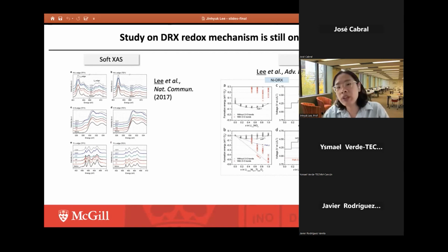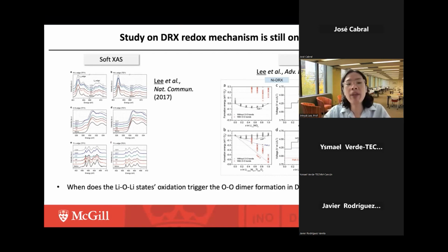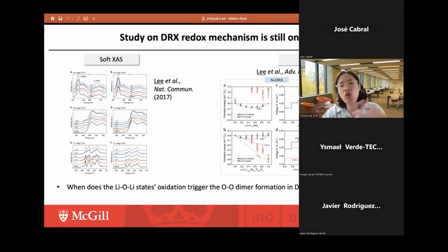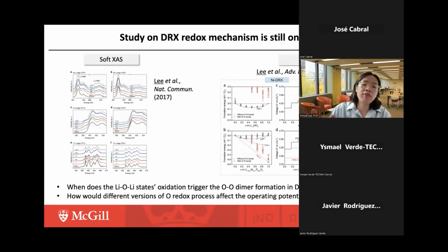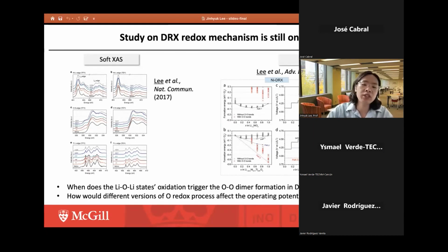Basically, I've been doing this further study to understand when this lithium-oxygen-lithium state oxidation triggers different types of oxygen oxidation mechanisms, including oxygen-oxygen dimer formation, forming superoxide or peroxide in the DRX structure. Because forming different versions of the oxidized oxygen species can affect the operating potential of the DRX and the cycling kinetics. We don't have to worry about it here. If you're interested, just read the paper. But anyway, more studies need to be done on this DRX material to make it better.